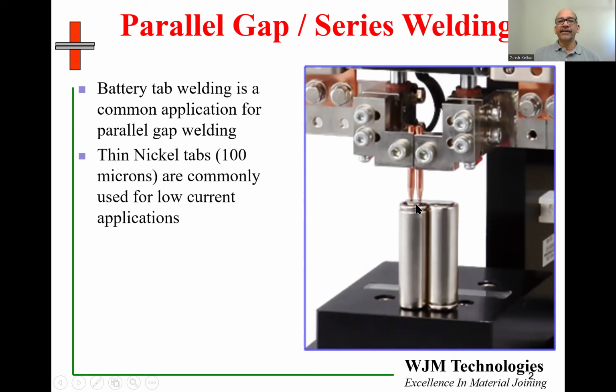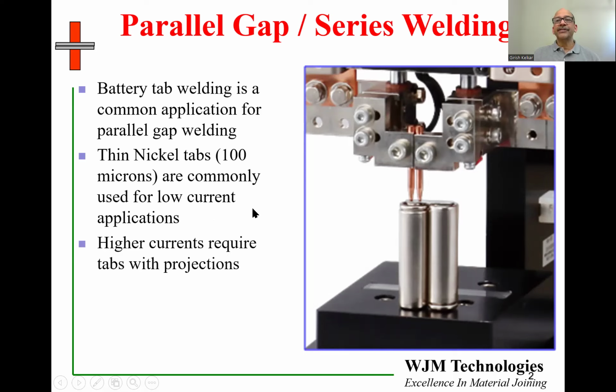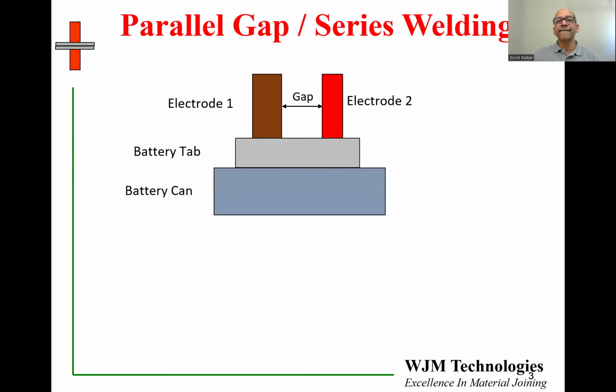Usually, for low current applications, a common use is for nickel tabs to be 100 microns thick. However, higher current applications may require thicker nickel tabs or composite nickel tabs, at which point you also need projections on the tabs to localize and focus the current exactly at the location where you want.